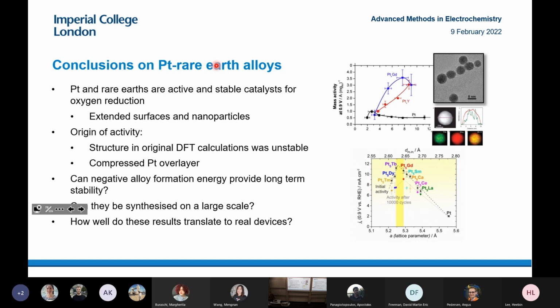Even so, I think it was still a really interesting line of work, and it attracted a lot of interest from industry as well, because through this kind of theoretical screening we essentially found a new class of platinum alloys for oxygen reduction. It still hasn't been proven completely, but this negative alloy formation energy could provide long-term stability. The big challenge is to synthesize it at large scale and test it in a device, which requires a lot of optimization.